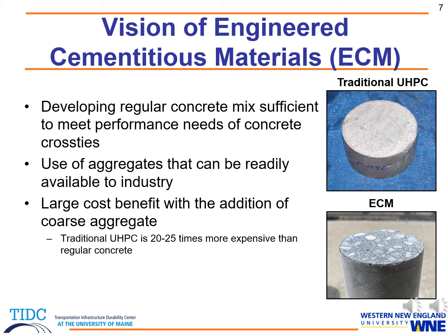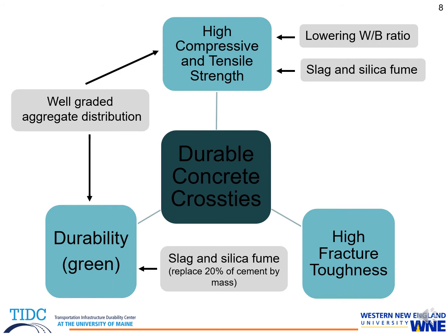Right from day one, we've always wanted to keep the ECM marketable, being that our vision is more industry-based. ECM would be a good candidate for high-rise buildings with small column designs, also precast concrete girders for bridges. The strengths we've achieved with our ECM have been 3,000 to 5,000 psi stronger than typical concrete used in bridge girders. Thus far in our research, we've been able to tackle achieving high compressive strengths and tensile strengths as well